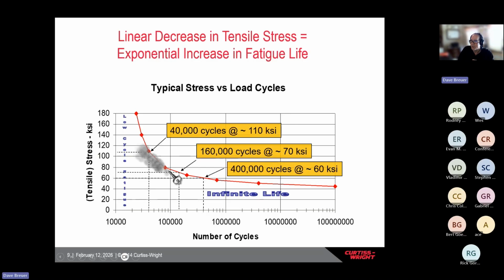But where this curve is starting to flatten out, you'll see that if you're getting 160,000 life cycles here, you're now getting close to 400,000 cycles here. So what it's saying is that the more fatigue cycles a part has before you shot peen it, the greater the improvement. So when I was throwing out that you could get a 3x up to a 10x extension in life, the more cycles the part is getting before shot peening, the closer it's going to get to that 10x or better improvement.